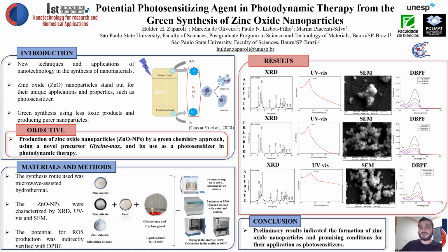Through the photobiophysical characterization, we verified that the solution containing only DPBF, after 19 seconds of radiation of UVA light, showed a reduction of the initial to final absorption band by 25% in the DPBF solution, with the addition of each solution of nanoparticles made with zinc acetate, zinc chloride, and zinc nitrate. We observed a peak absorption reduction of 21%, 22%, and 20% respectively.